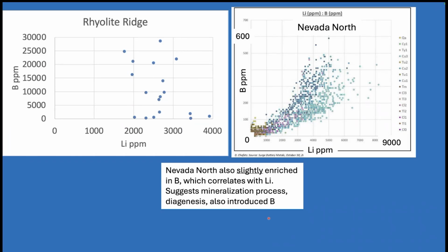And just a quick comment about boron. Rhyolite Ridge, of course, has very high boron. It's a lithium boron deposit. And the other places don't have boron data except for Nevada North. And maximum boron concentrations there are only about 600 ppm, much, much less than Rhyolite Ridge. But you can see there's a correlation between increasing lithium and increasing boron. So it looks like the mineralization process enriches boron in a combination of dissolution of the source material and evaporation. But the starting material is critical. The starting material at Rhyolite Ridge probably had a lot of boron.